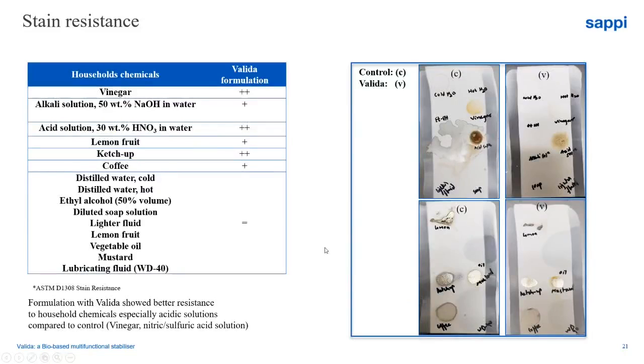Among the different benefits that Valida delivers, we have seen the stabilization one, but Valida is also able to improve the chemical and mechanical resistance. So not only the rheology. From the table here on the left and the pictures here, we can easily understand that Valida improves the stain resistance of the coating layer or formulation, especially towards acidic solutions, for example vinegar, lemon, and nitric and sulfuric acid. And we can see here in the picture the difference between the reference formulation without Valida and the one with Valida. Much lower stain on the layer.